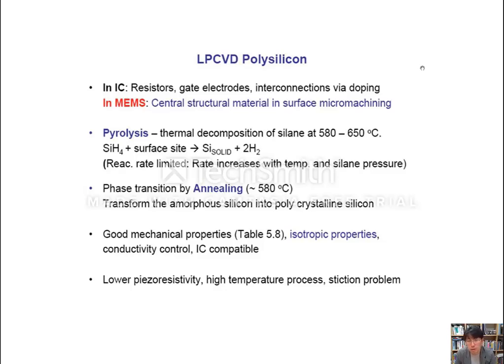So this particular process is pyrolysis. To make that LPCVD polysilicon, we thermally decompose silane at a particular temperature on the surface, and then you build silicon here. In this process, you need to control the temperature and the silane pressure, and then you can control the reaction rate. Phase transition is done by annealing, so you heat up. Using this process, you can transform the amorphous silicon into polycrystalline silicon here.